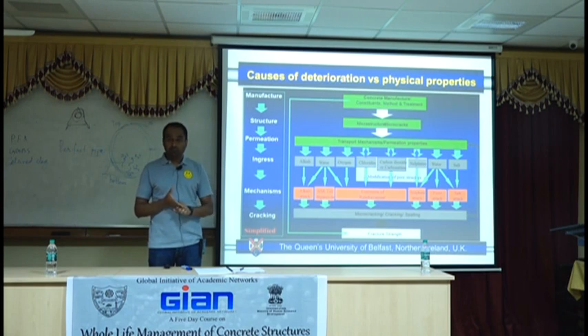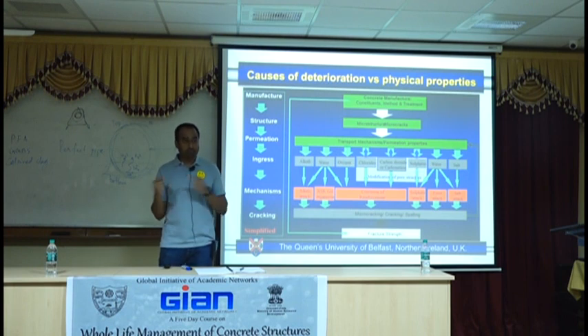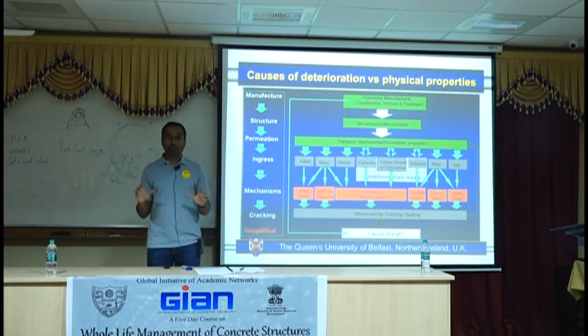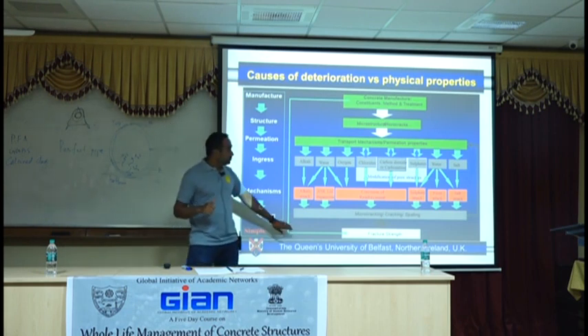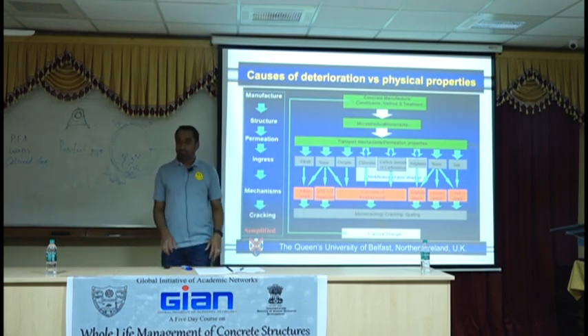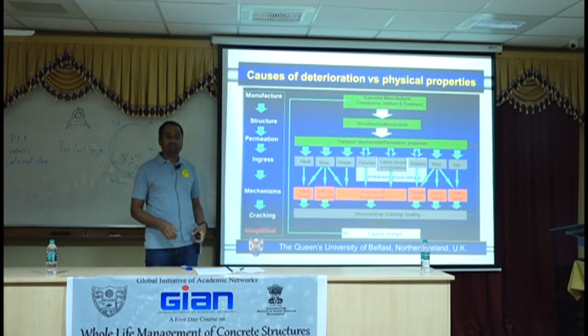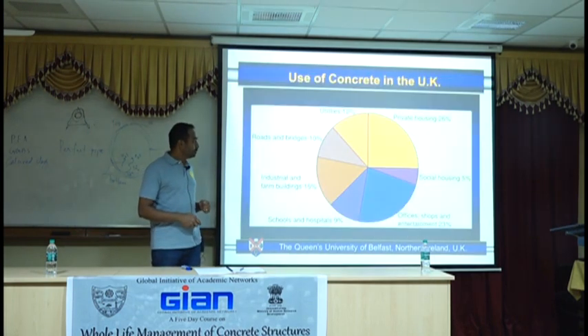Provide sufficient cover. If the cover concrete decides to remain in place and decide not to move, it's not going to corrode, because it has to yield for corrosion to progress. It'll start corroding, but it'll stop. So good cover, reasonable strength, low diffusivity. This is your best bet to making good concrete. Are we clear? Brilliant.